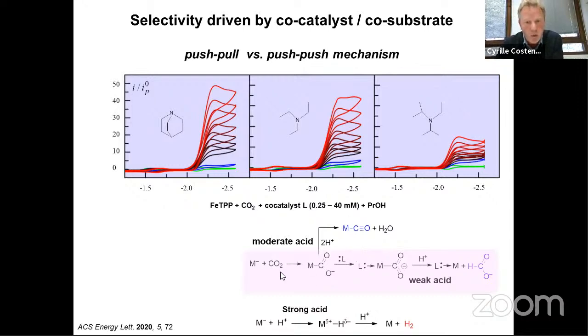So again, we propose that what happens in the presence of a moderate acid is that actually you do not go through the formation of the hydride, but you bind CO2, and then in the presence of an amine, for example, you push more electrons by binding the amine on, for example, the intermediate iron 2 CO2 minus, and so then you make the breaking of this metal-carbon bond easier, and then in the presence of a weak acid, you will end up with formate.